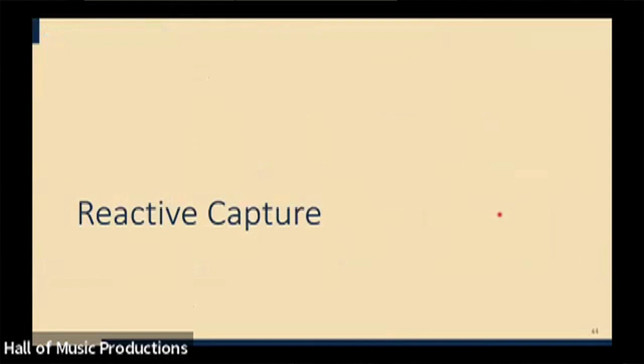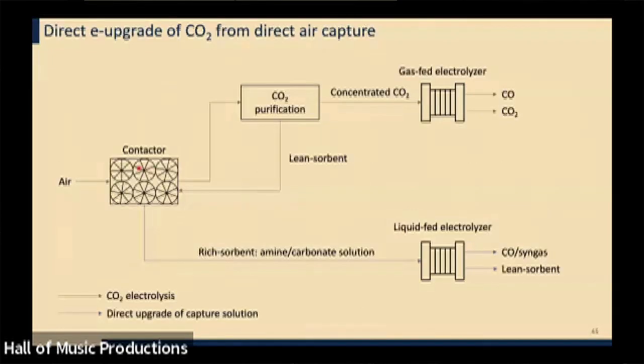And the approach that we've taken is one known as reactive capture. So first I need to just highlight the legacy approach that many groups are pursuing and is now growing in its adoption and its performance, which is first to take your gas, be it air or be it flue gas, contact it to either a liquid or a solid sorbent, but then use typically thermal swing or pressure swing or vacuum swing to release that CO2 and feed that into one of these electrolyzers I've been speaking about. Well, that comes with quite a few inefficiencies. And so recently, this community of folks in reactive capture started to ask, could we use the liquid that captures the CO2, and which of course now has a high concentration of the CO2 within it, could we use the liquid and feed that directly into our electrolyzer?